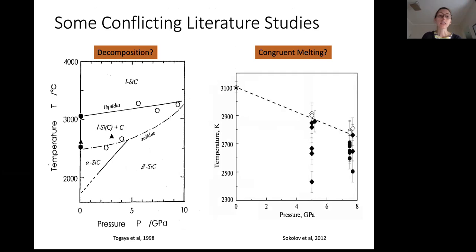Right, so several studies had looked at the high pressure behavior, but with some conflicting results. Over here on the left, I'm showing results from Togaya et al. in 1998. They're looking at pressure versus temperature, and they find that silicon carbide melts by decomposition, represented by this liquid silicon plus carbon region of their phase diagram, and that as pressure increases, the temperature needed to begin melting also increases.